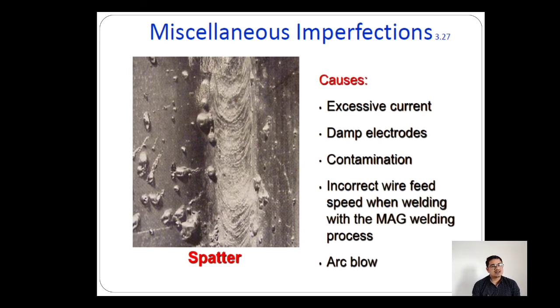This is called spatter, friends. I think most of the people know about that. Once the welder is using higher current, this kind of hot globular particle is spread on the parent metal, and this is also very dangerous for the parent metal because it may also create a hot spot in the parent metal. So the main reasons for spatter are excessive current, damp electrode, contamination, incorrect wire feed speed when welding with GMAW or MAG welding process, and arc blow. Arc blow we already discussed in the last class, friends. Once our material is magnetized and we are trying to weld it, at that time high spatter is created.